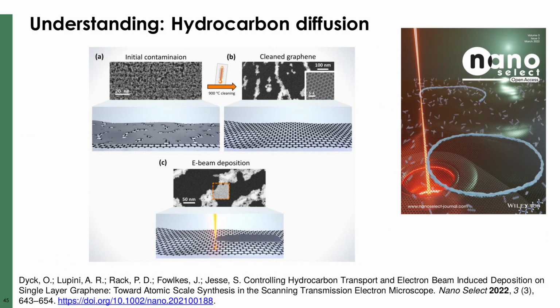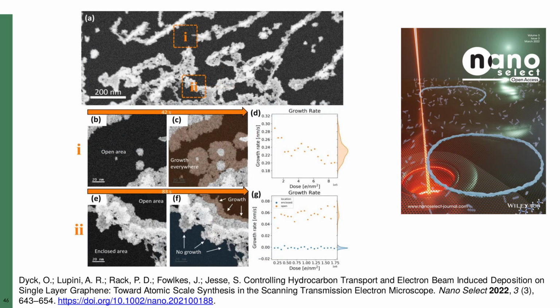Here's an example of a sample that starts out coated with visible contamination. After heating, much of it becomes clean, but if you zoom in, you start to get hydrocarbon deposition. So even though the graphene appears clean, there are still mobile hydrocarbons that we can't see that interfere with us. Here I was examining their behavior. In Area 1, I acquired a video for 42 seconds. The first and last frames are shown.